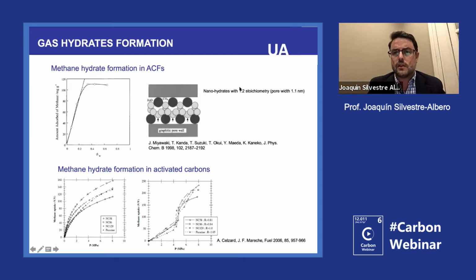At this time, they were working with activated carbon fibers with a very narrow pore. I think the size was 1.1 nanometers, so it's lower than the crystal size of the hydrate. But the group of Professor Kaneko was predicting that there should be something like a nanohydrate being formed in the cavities. They were predicting a concentration of methane in the walls of the carbon, and then the water molecules making a zigzag between these methane molecules. So that was the prediction for these nanohydrates.